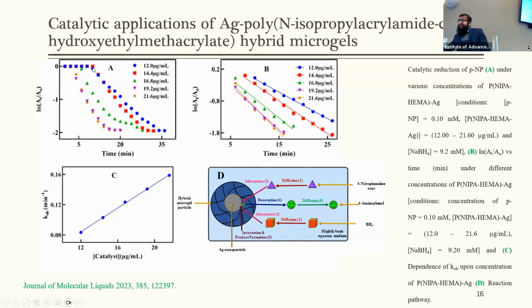This induction time can be explained on the basis of the pathway of the catalytic reduction of 4-nitrophenol. Reactant molecules diffuse from the bulk region to the surface region, and they take some time to reach the surface of the silver nanoparticle. This induction period is the time required for the reactant molecules to reach the surface of the metal nanoparticles. Moreover, the rate constant was observed to be a linear function of catalyst concentration, which indicates that the catalytic reaction is occurring on the surface of the catalyst.